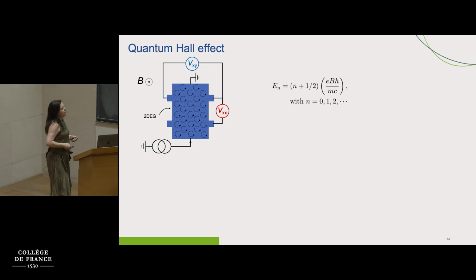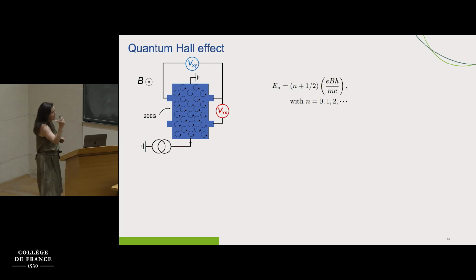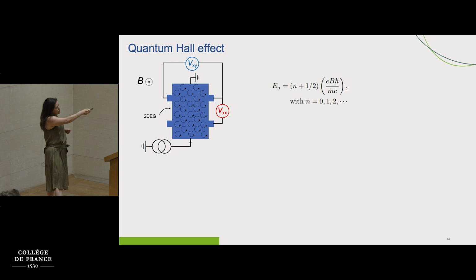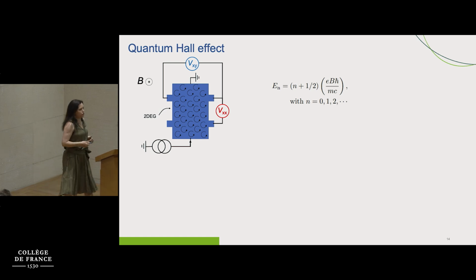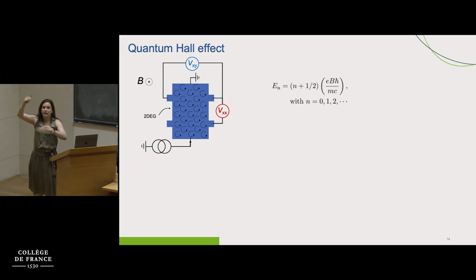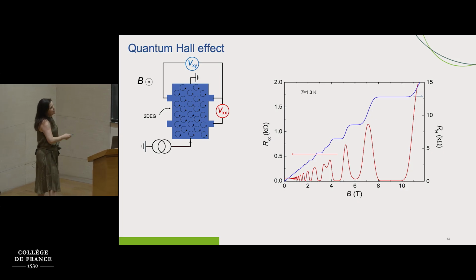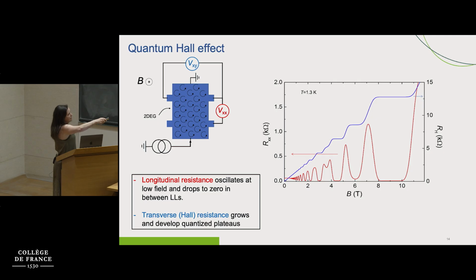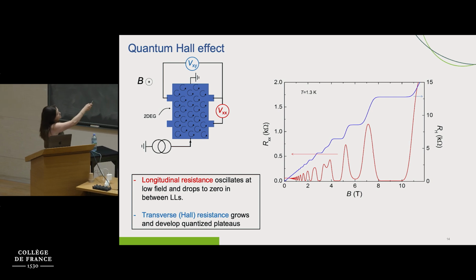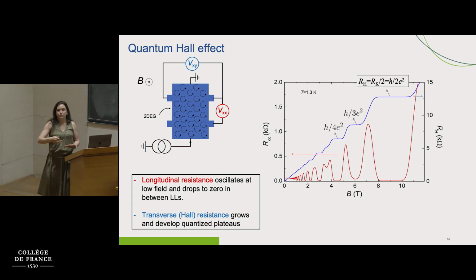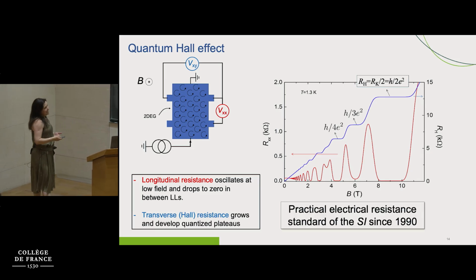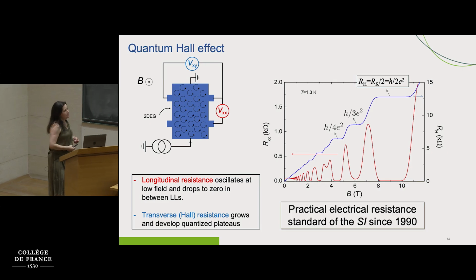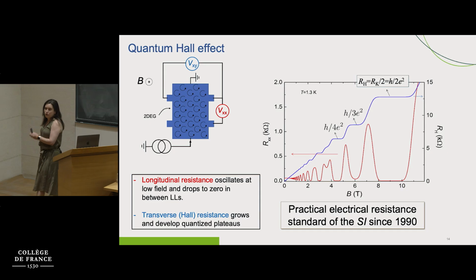So let's say that we have the same two-dimensional electron gas with a magnetic field applied out of plane, and we're going to measure two quantities. We are going to measure the longitudinal voltage or resistance and the Hall voltage or resistance. You need to remember that now you have Landau levels that are equally spaced in this case. So when we measure the longitudinal resistance, what we are going to see is an oscillation, a very fast oscillation at low magnetic field, and then it eventually becomes slower, and in between two oscillations, this longitudinal resistance drops to zero. At the same time, the transverse resistance is going to describe plateaus, and these plateaus are going to be quantized, okay, in terms of fundamental constants of nature. And this is so well quantized that, in fact, this value is the practical electrical resistance standard of the International System of Units since the 90s.